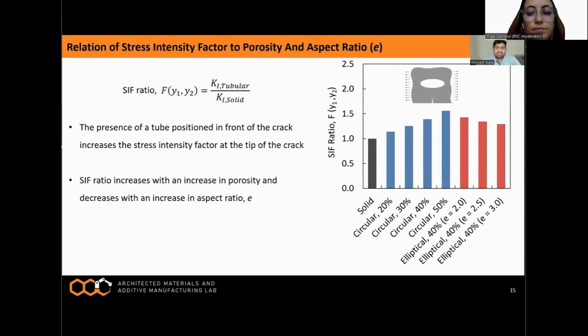Based on our discussion in the last slides, we have calculated the stress intensity factor ratio for different porosity and aspect ratio of tubes. For the solid system, in the absence of the tube, the SIF ratio is 1. That makes sense. We can say that the presence of the tube positioned in front of the crack increases the stress intensity factor at the tip of the crack. The SIF ratio increases with the increase in porosity, and it decreases with the increase in aspect ratio, which is an interesting finding.